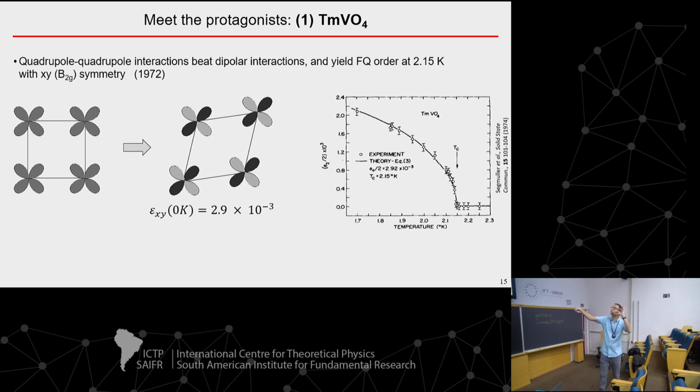All right, so if I want to look at this sort of graphically, looking down the c-axis, I have the unsplit doublet at a high temperature, and I've drawn it in the xy basis. That splits spontaneously. So now I have more population of one state than the other. So that's the XY quadrupole, drawn here in terms of the occupancy of the actual orbitals, but just showing these as XY, as sort of d orbital things. And this clearly, because of that bilinear coupling to the strain, you have a concomitant strain that develops spontaneously there. And right, great, you can measure that strain. This was also done in the 1970s. There's the development of the spontaneous strain at this continuous phase transition.